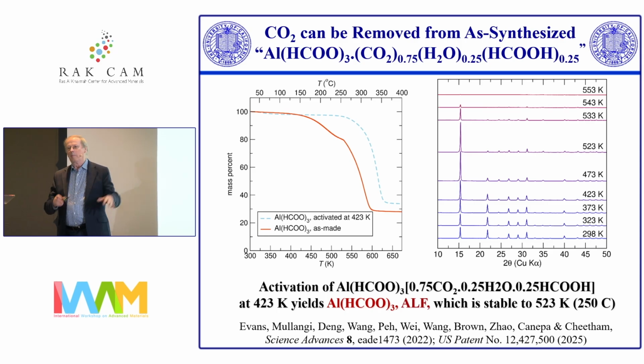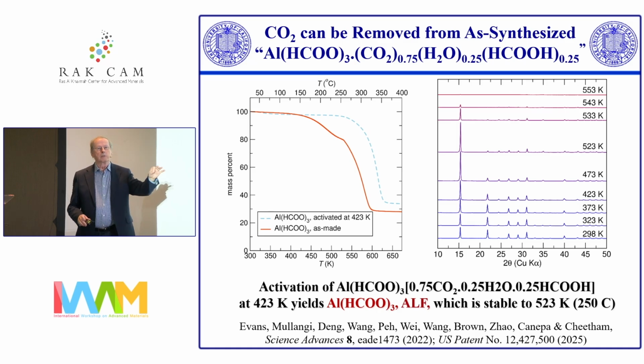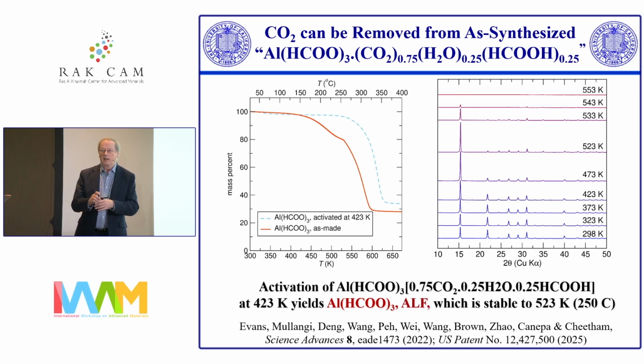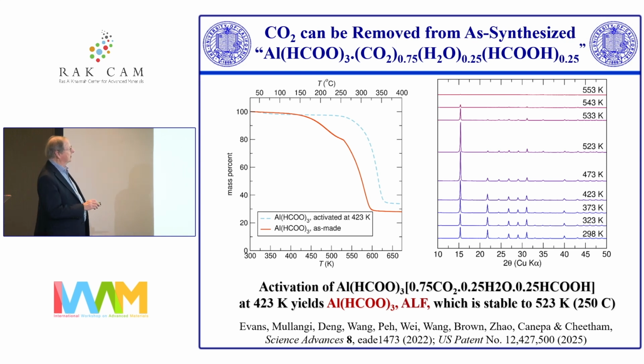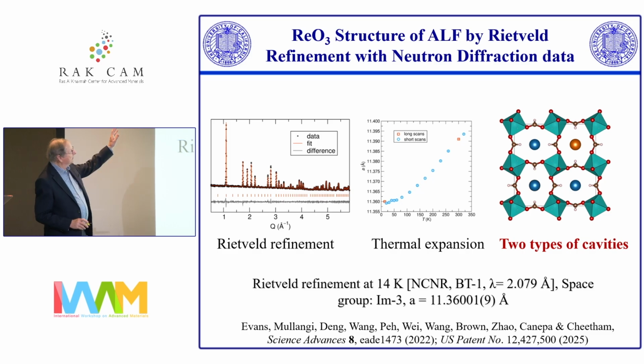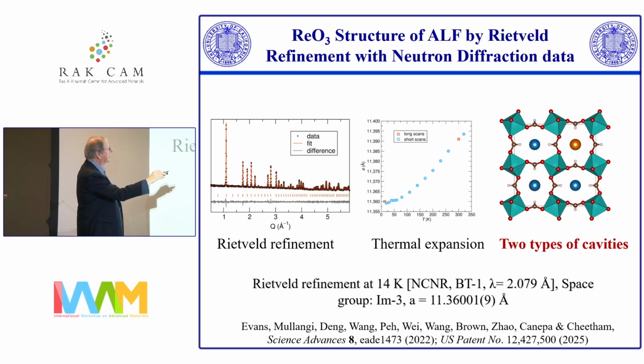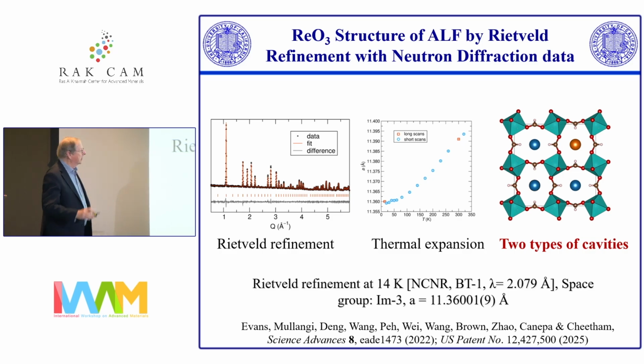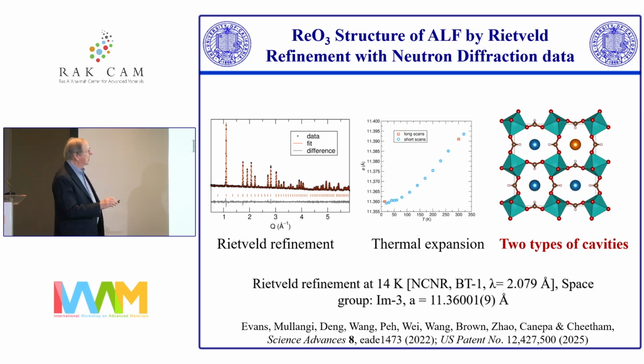We've just been doing some NMR work, which I don't have time to discuss, but in most of the samples we make actually don't have CO2 in the cavity, it turns out. They've got formic acid in the cavity, and they've also got some carbonic acid in the cavity. And you can see this in the NMR. Notwithstanding that, having activated it and done the crystal structure of it very, very carefully, it shows some negative thermal expansion or zero thermal expansion at low temperatures.